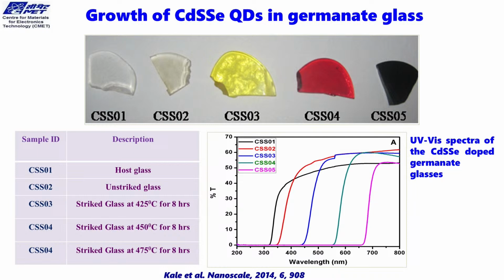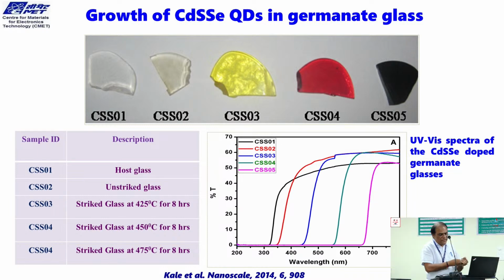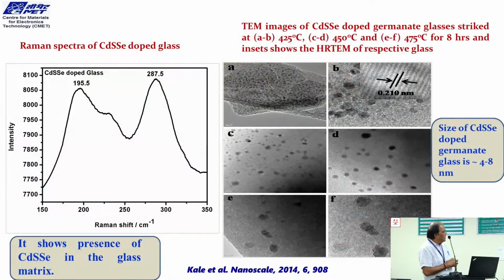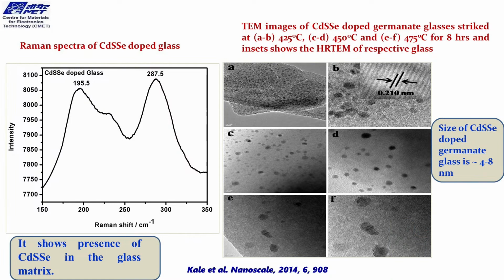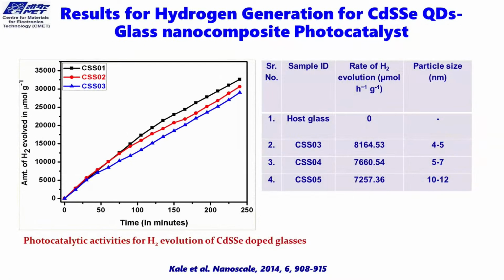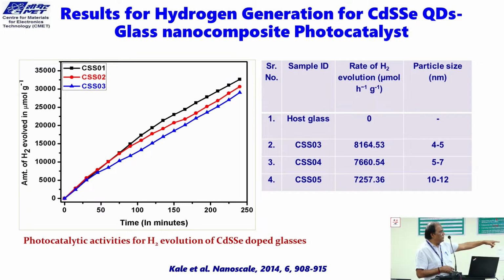There is a huge shift due to the particle size, and because of this particle size, you get different properties. These are all optical properties; there is a change in optical properties. Since these particles are very tiny and small in number, it is very difficult to identify. So we did Raman spectra and found that these particles are nothing but CdSSe particles. And for hydrogen evolution, when the particle size is very low, 4 to 5 nanometers, you get a very huge amount of hydrogen evolution as compared to larger particles. And these particles are very stable.